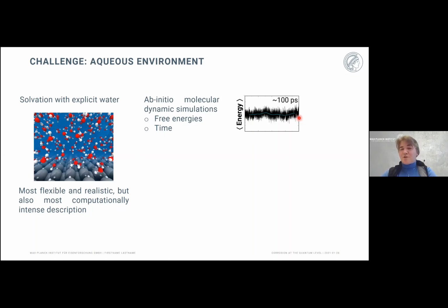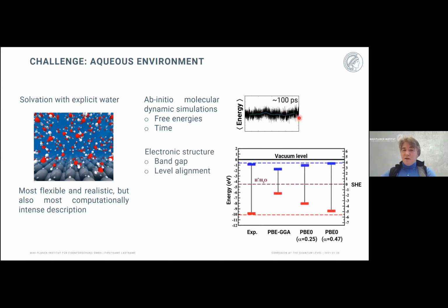Still, as Sudarsan will show you, even with the shorter trajectories we can still learn a lot about mechanisms. When we go to an explicit water, one thing we have to consider is also the electronic structure. In the implicit solvent, or even when we consider just a few layers, we don't really care so much about the band structure or the electronic structure of the water, or we can't access it. But water has a band gap, and experimentally this is measured to be in the order of 10 eV.